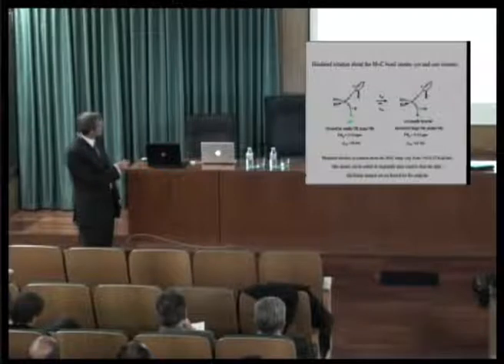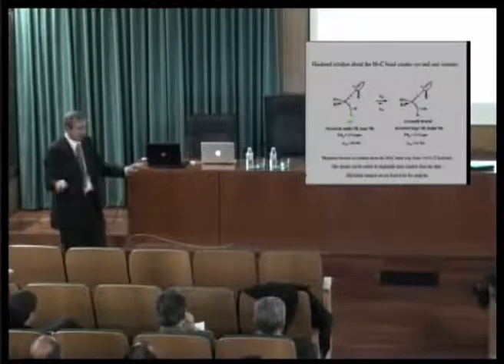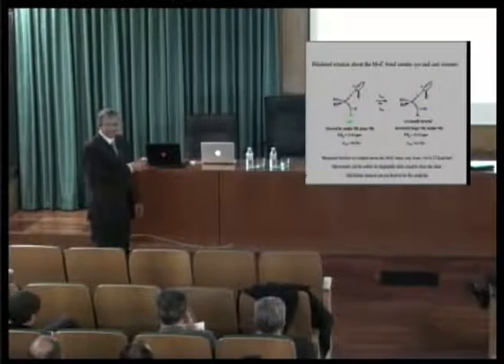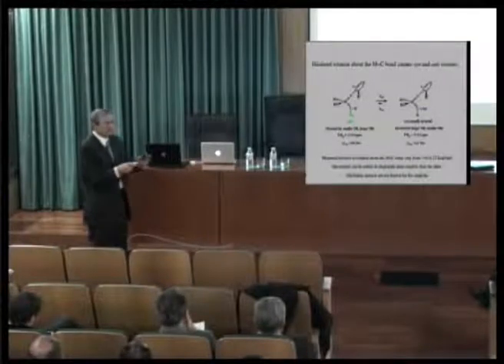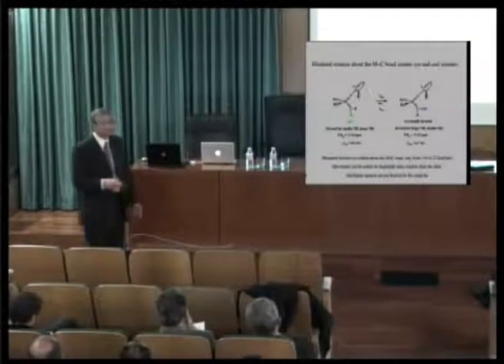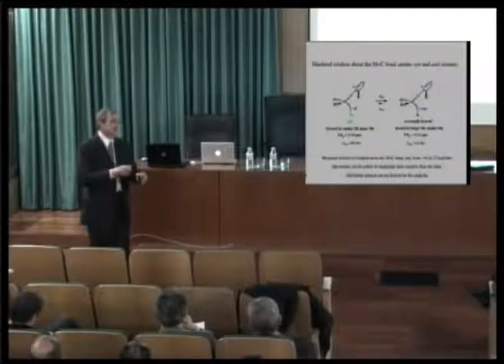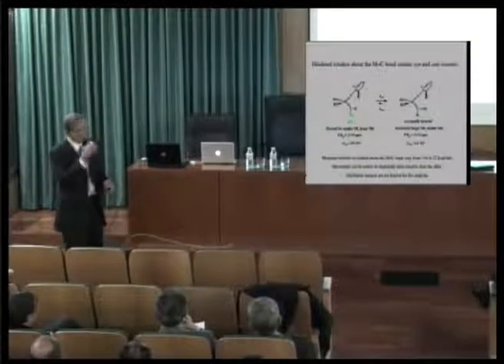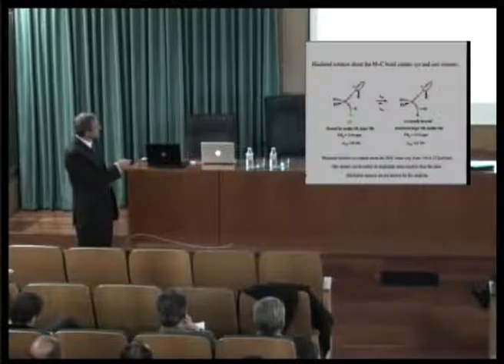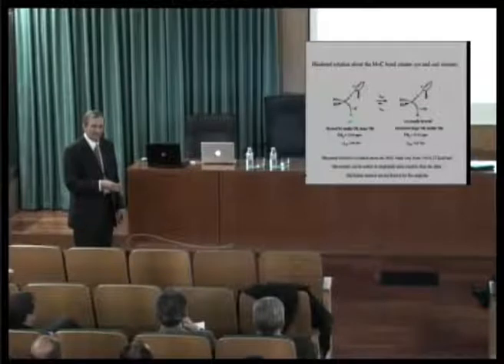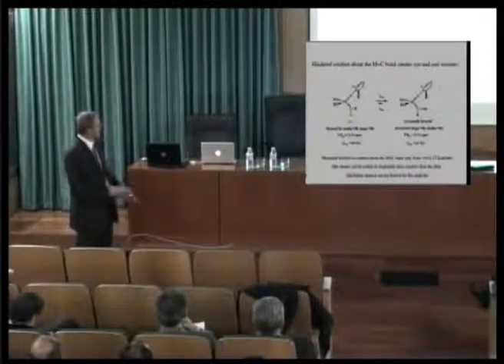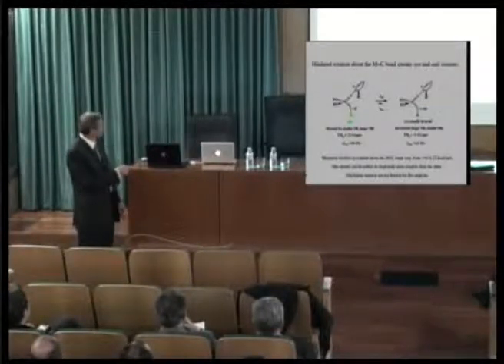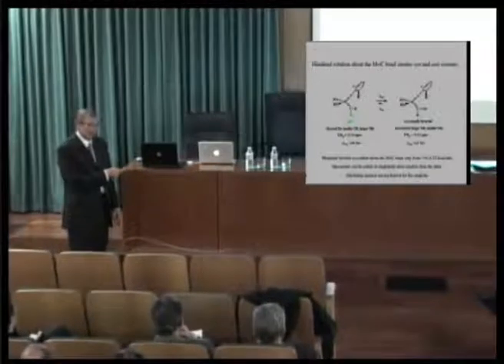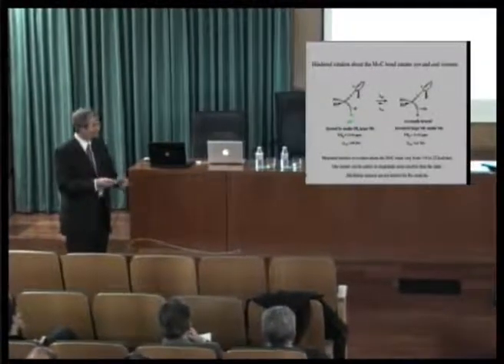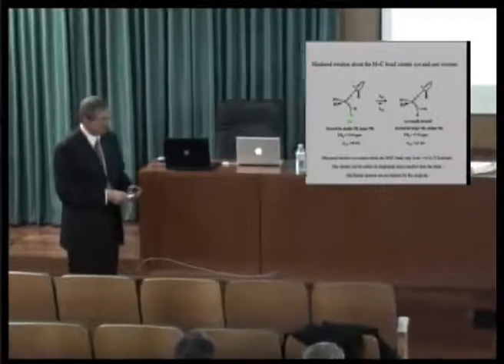And the one where this is pointing away, kind of a trans or anti-isomer. The rate of interconversion of these in the absence of an olefin can be very, very fast, as fast as 10 or 100 per second, or very slow, 10 to the minus 5 per second. So many orders of magnitude difference in rate of interconversion, and since they are different compounds, they react differently, they behave differently, and so it's a complicated situation, especially if they interconvert, or even if they don't, to deal with.